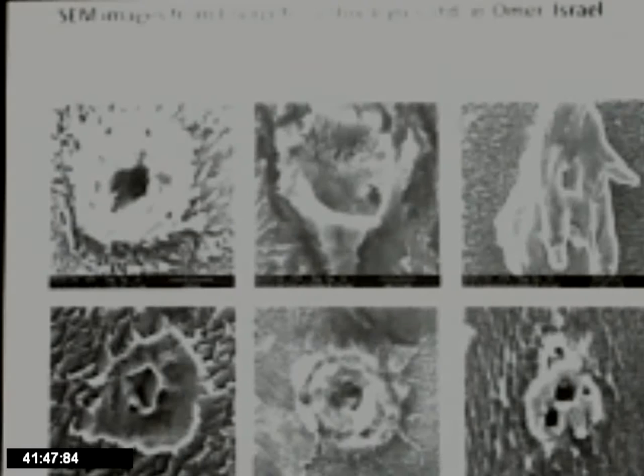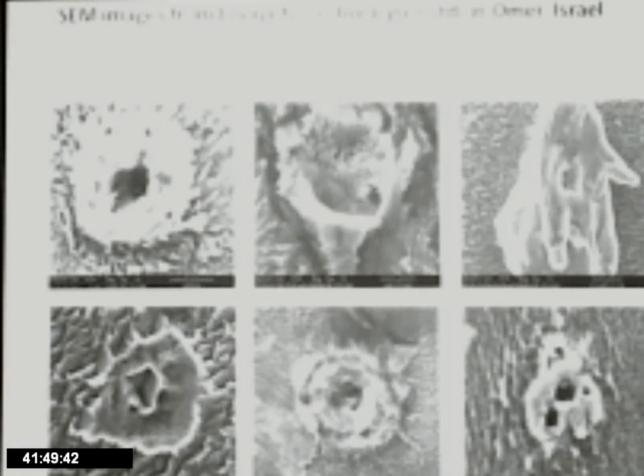But again, the origin of these microcraters is still under intense debate. Many people think, from results they get in impurity analysis, that the distribution there versus the rolled palladium outside the region of the heat release suggests a thermal anneal. But again, a lot of controversy. It'll be interesting to see how that resolves.